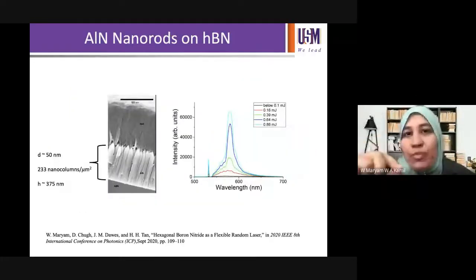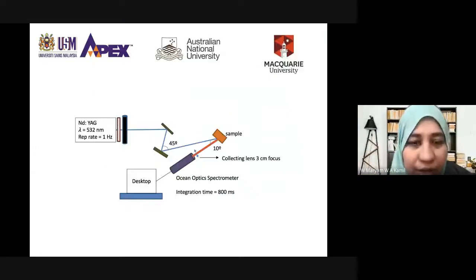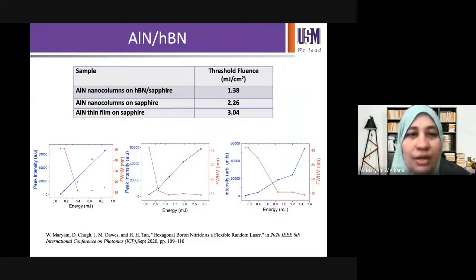So what we notice is that for aluminum nitride, when we have hexagonal boron nitride as the layer, very thin layer, it's only like 10 nanometer or so, very thin. Okay, and what we notice is that that layer actually reduces the threshold compared to when we had nanocolumns, but it was just on sapphire. When the aluminum nitride were thin film, the threshold was even higher. You can still get random lasing, but the threshold was high.